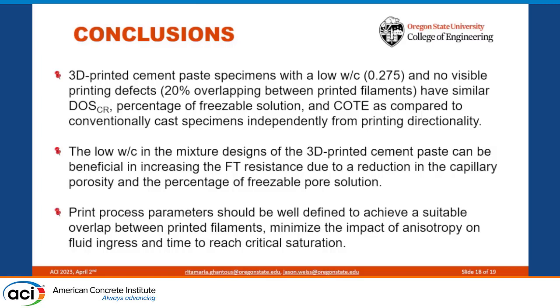So in summary, samples with good overlapping have similar critical degree of saturation value, similar percentage of freezable solution, and similar coefficient of thermal expansion compared to conventionally cast samples, independently from the printing directionality. And the low water to cement ratio of this mixture is very good for reducing capillary pores and freezable solution, which increase the freeze-thaw damage of printed materials. And print process parameters are very important because they impact fluid transfer, and anisotropy matters in that case.